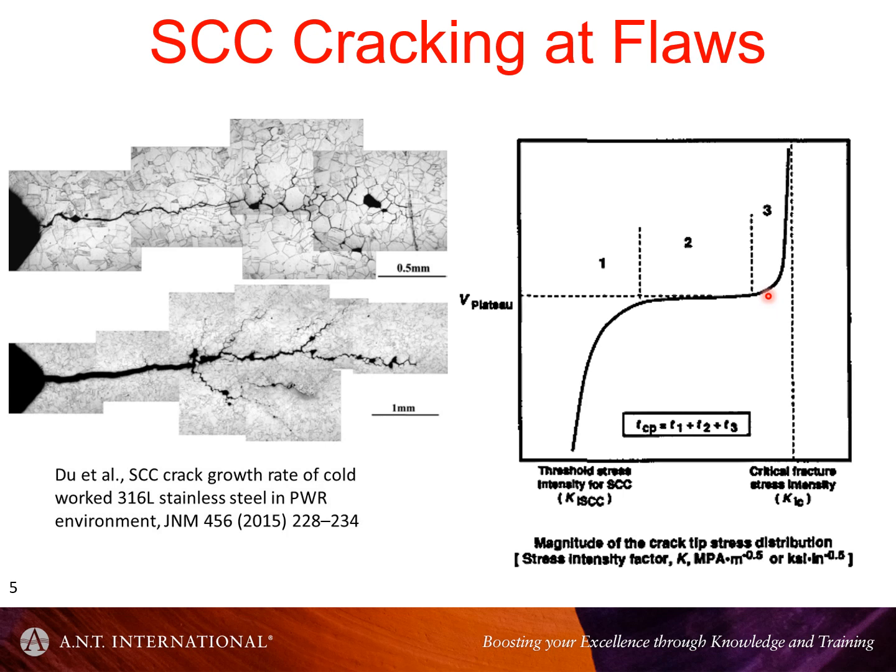So the difference is with delayed hydride cracking, the hydrogen comes from within the material, and with SCC, it comes not from hydrogen necessarily, but from oxidation, some product, something that's going to fail in a brittle manner, comes from outside, from the environment.